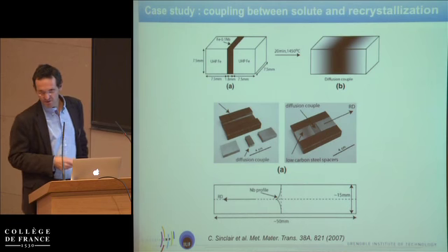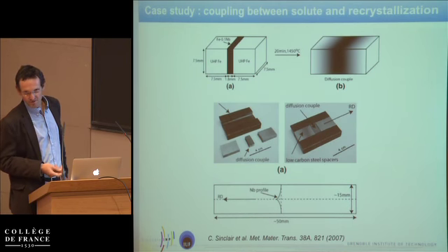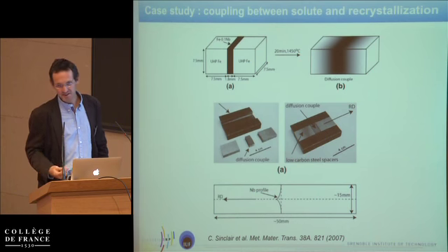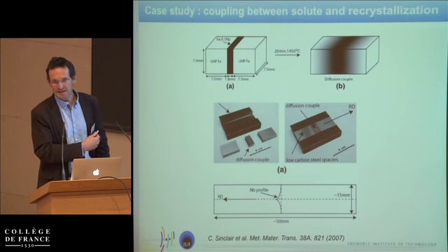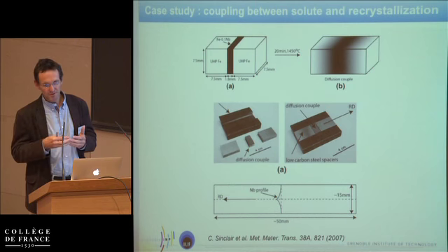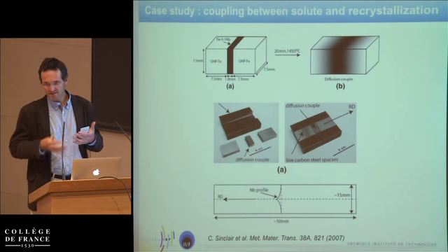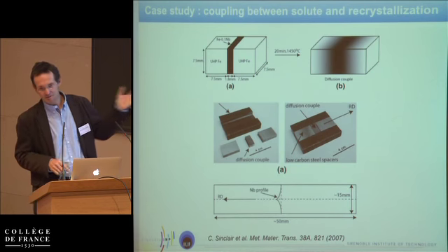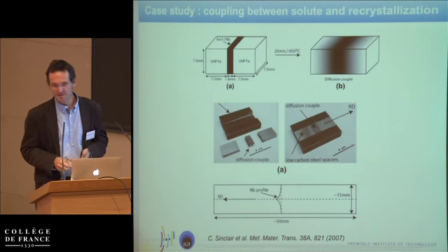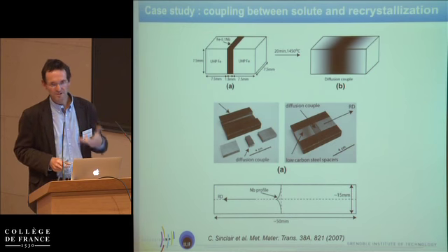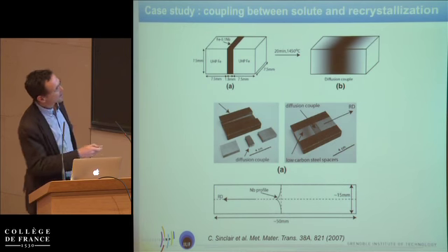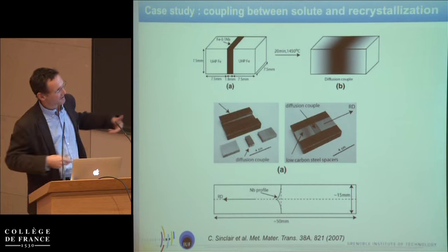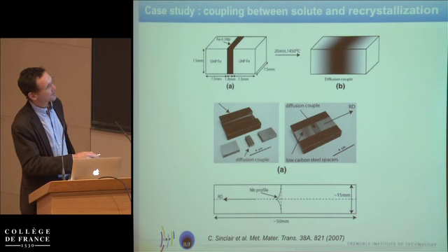So in order to look at recrystallization, of course, you need to make a diffusion couple, but then you need to deform it, because if you don't deform it, then you can't recrystallize. And that's one of the points I was making. Making a diffusion couple, if it's brittle at the interface, it's not good, because then you can't study anything that's related to deformation. And recrystallization is one of the cases where you need your diffusion couple to be deformable. So here they managed to deform it by inserting it into different pieces and rolling it. And then you've got